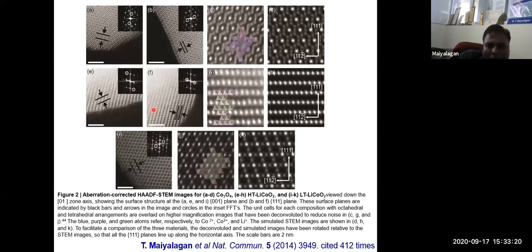Then we look at the TEM images, aberration corrected TEM images, to look at the layered structure and spinel structure. And these, A to D, are cobalt oxide spinel structure. You can see the atoms very clearly, how the spinel structure has been arranged. And E to H is high temperature lithium cobalt oxide, where you can see the layer structure. You see the H, how the layers, atoms have been arranged in the layered structure.